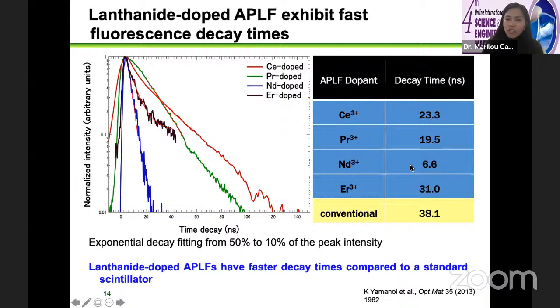Neodymium ions would give us the fastest decay time, and that's also because neodymium gives the shortest luminescence wavelength, which is around 172 nanometers in the vacuum ultraviolet region. But still we chose praseodymium because it has a fast enough decay time, and at the same time the luminescence emission is in the ultraviolet region.